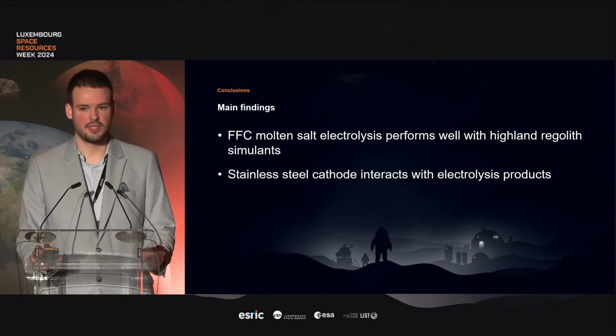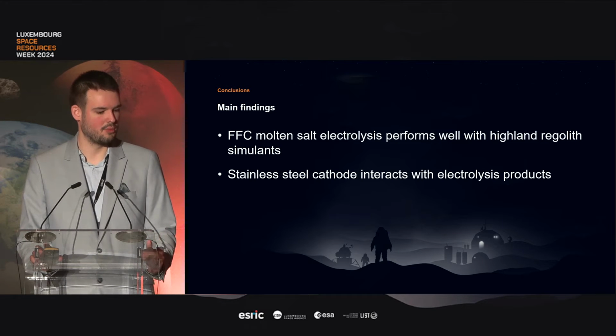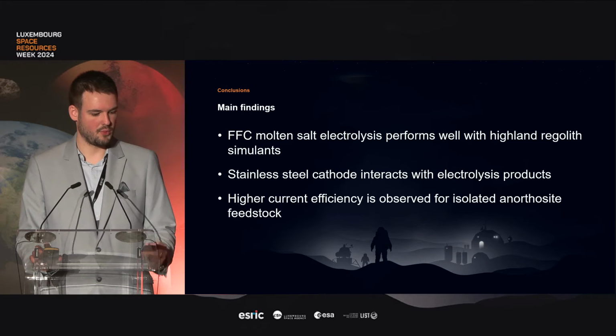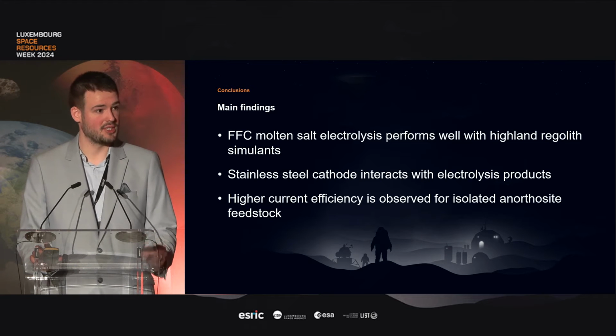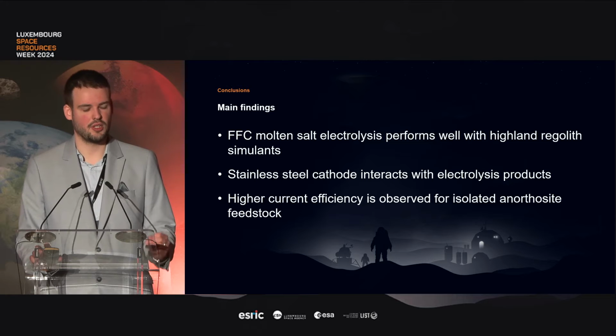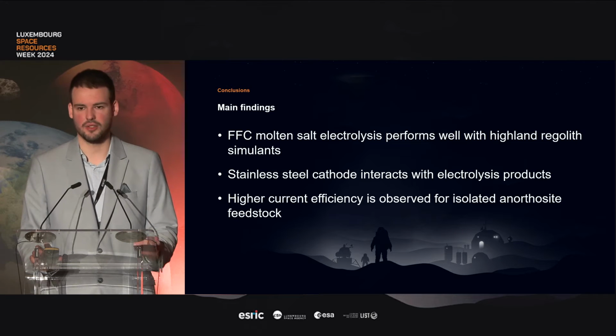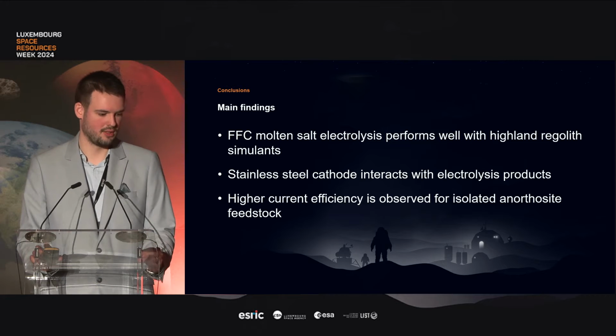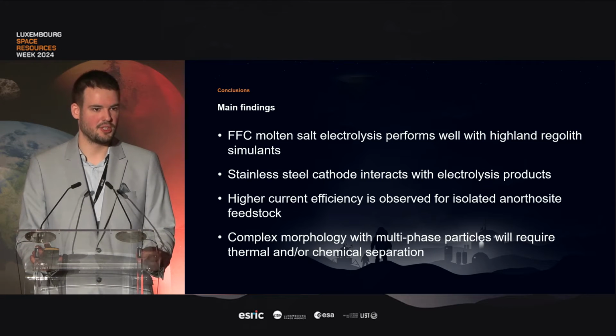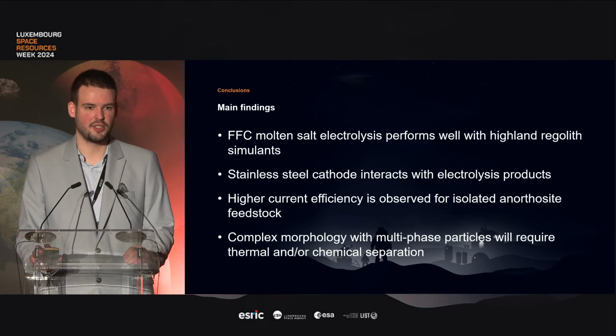The few points we found. First of all, the FFC process works quite well with Highland regolith simulants, which is always nice to know. We do have some material challenges that still need to be addressed. For example, the stainless steel in the cathode does tend to interact with the metals we are producing. We seem to observe higher current efficiency for anorthosite, which is a good argument for prior beneficiation of the feedstock. We need to look a bit further into that to confirm this and also to find out why. And then finally, the complex morphology will make physical separation really challenging.